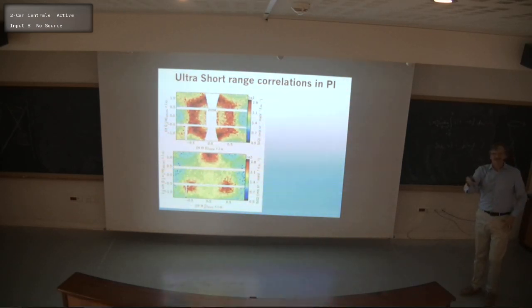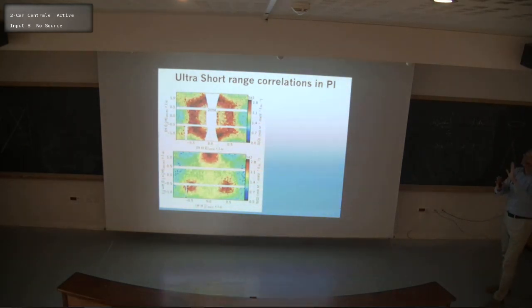So, we were looking at the spin ice compound where we had this manifold of states. So now we're looking in the paramagnetic insulating state near the Mott insulator transition, and we find really broad features. In fact, it looks just like a highly frustrated magnet of some kind. That was what sprung to mind when we saw this. So that's curious because we are really close to the phase transition into the antiferromagnetic insulating state. And so we were puzzled by why the correlation length is so short in the system.